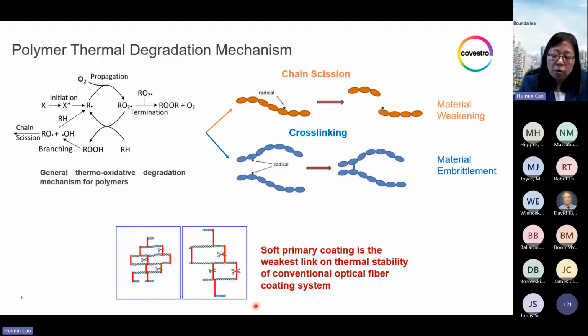This simplified diagram explains why developing a low modulus primary coating for high temperature durability is so much more challenging. If you assume the same number of chains breaking down from the thermal oxidation process, the softer primary coating with much fewer crosslink points will suffer much more quickly, losing coating integrity, than the high crosslink density secondary coating. And this is why the primary coating is the weakest link when developing this dual layer, high temperature coating system.